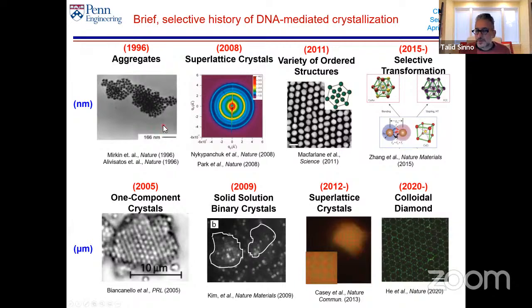The basic idea is the same. The difference is that at the nanometer scale, the size of the DNA strands put on the surfaces is significant compared to the particle size. The other big difference is that it's pretty hard to see and image the structures you get at the nanometer scale. It's much easier to do this at the micron scale, where you can use optical microscopy to image the structures. Very loosely speaking, back in the late 90s, this was proposed both by Mirkin's and Alivisatos's groups as a way to drive self-assembly.